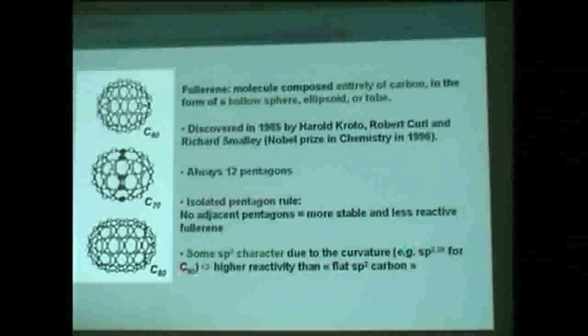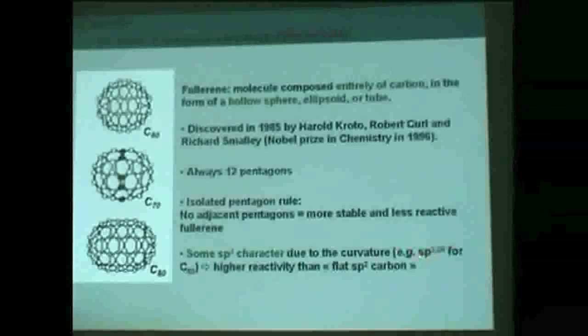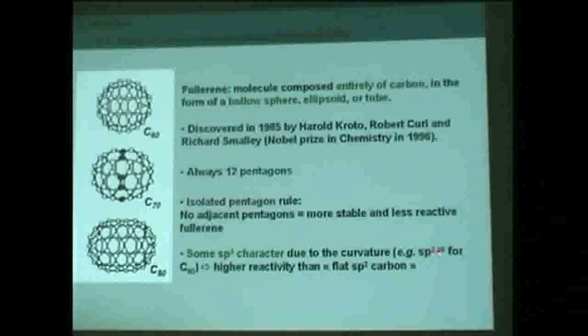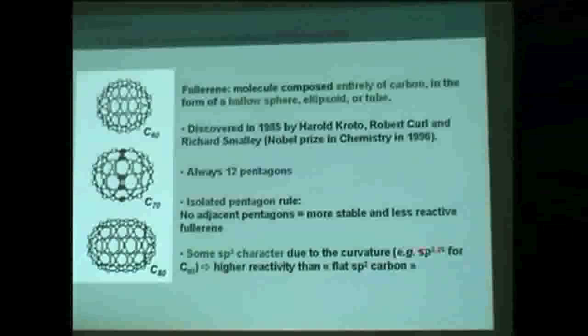For instance, C60 is considered to be something between sp2 and sp3, sp2.28 as experimentally measured. So you see that there is quite a lot of sp3 proportion in C60. And in C60 all the carbons are similar, so all are sp2.28. All those carbons have the same proportion of sp2 and sp3 locally.